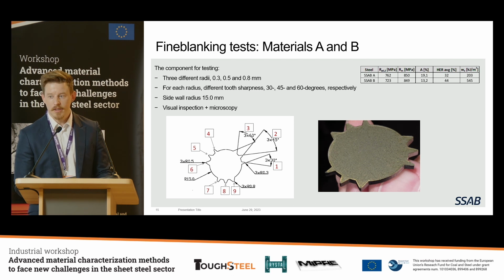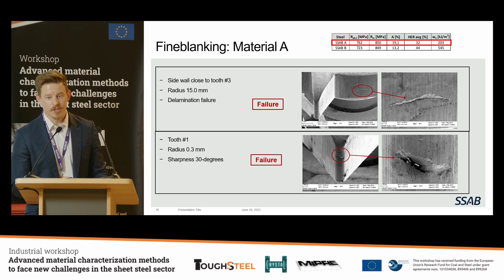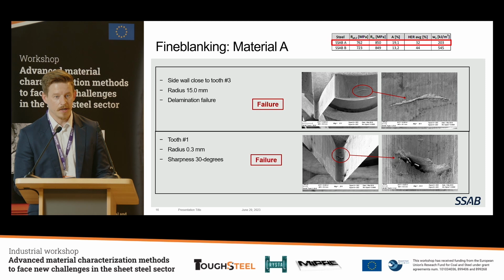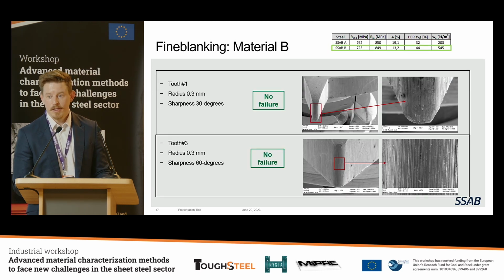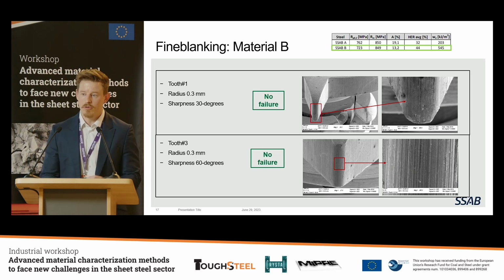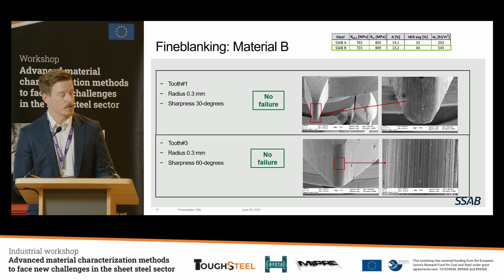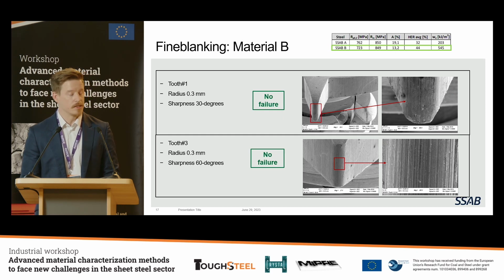This is a special design that we have, including different tooth radiuses, different cutting angles, and we are using zero cutting clearance in fine blanking, and we are monitoring whether we see any cracks or defects on the fine blanked cut surface. And again, the same steel grades, and maybe you can already guess the kind of results and story. Steel A is showing defects on these fine blanked surfaces. I wouldn't recommend this grade for fine blanking purposes, but steel B, we couldn't find any defects, even with the most challenging tooth radiuses. So it's absolutely perfect for this application. And again, the thing that is differentiating these materials is essential work of fracture.